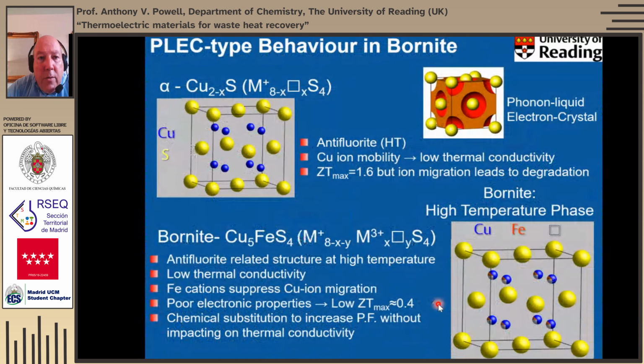So to finish, I just have a few slides on sort of that phonon-liquid electron crystal type behavior. And the archetypal example in many ways are the copper sulfide and copper selenide of this type, which at high temperatures are anti-fluorite type structures. And it's found that the copper ion mobility at high temperatures leads to a melting of the copper sublattice. So effectively, the anion lattice stays the same. The copper sublattice melts, and it assumes a liquid-like state. And that impacts substantially on the thermal conductivity and reduces the thermal conductivity quite markedly. And ZT maximum reaches about 1.6.